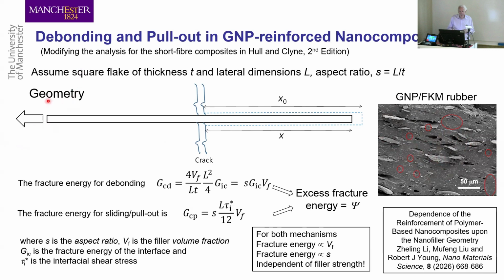And clearly, what happens is that when the material breaks, what the flakes do is they just debond and pull out. They're too strong to break. They don't break, they just pull out. So all the energy, all the toughening in this case is not due to the strength of the graphene, it's just due to mechanisms such as pull out and debonding. And you can go through the maths of it.